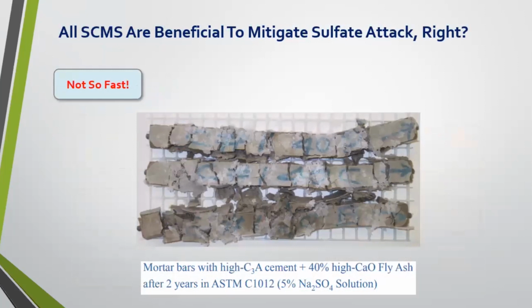So you might say, well, obviously, if I introduce SCMs, then I'm covered, right? Well, not quite so fast. The picture you're looking at here is mortar bars that were made with a very high C3A cement. So this might be a traditional type 1 with, say, an 11 or 12% C3A content, and then a 40% high calcium oxide fly ash. And this is after 2 years in a 5% sodium sulfate solution. And you can see the devastation here to the mortar bars.